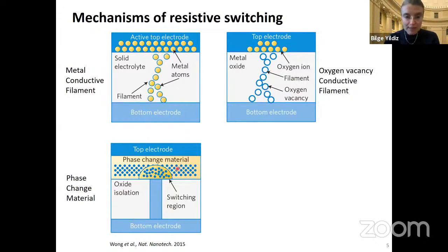A third process relies on electrically induced Joule heating and causing phase change between insulating and conducting phases of a given composition. So we call these phase change materials, again, electrically induced, but the underlying mechanism is heating to change from one phase to the other. So these are quite popular processes that have been investigated so far.